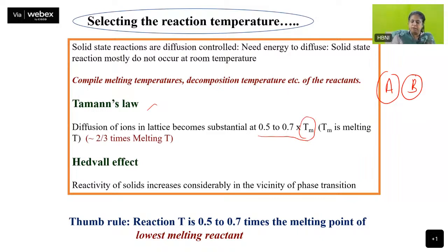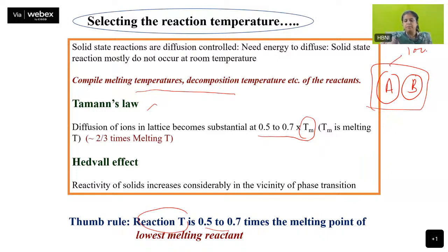Okay. And so what we want to do is, if we have two reactants A and B, we could have three, A, B, C, depending on what you need. We compile their melting temperature or decomposition temperature. Okay. And then what we do is, the reaction temperature is chosen as 50 to 70% of the melting point of the lowest melting reactant. If A melts at 1000 and B melts at 800, I will choose my reaction temperature at somewhere around 500 to 550. That is the thumb rule. Again, it comes by experience and a lot of percentage of lab work comes by experience. Okay.